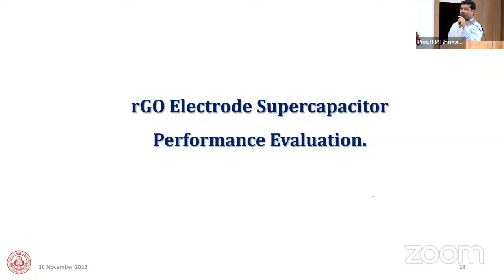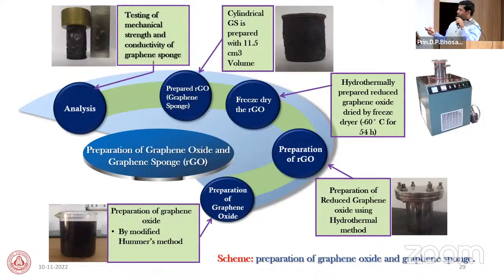Then I prepared RGO electrode for supercapacitor application. Actually, this is negative electrode, and for the testing of asymmetric device preparation. So at first, I prepared graphene oxide solution by modified Hummers method, and then this graphene oxide is dispersed in some amount of water, and this solution is placed under hydrothermal bomb at 150 degrees centigrade for 12 hours, and then after 12 hours, it gives RGO, reduced graphene oxide.